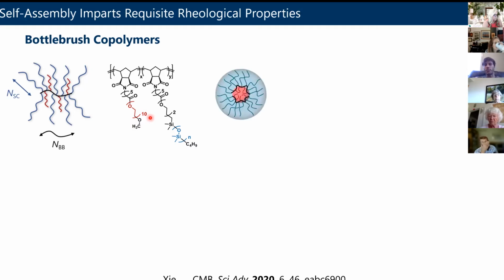Now, when you do this, if you pick the chemistry right, like polyethylene oxide and polydimethylsiloxane, they don't like each other. Those polymers, they want to be like your salad dressing. If you mix them together, they would phase separate. They would try to create layers of all polyethylene oxide and all polydimethylsiloxane. But we've linked them together with covalent bonds. So they can't create layers at the visible length scale like your salad dressing, but they try to do something similar at the nanometer length scale, where all of the red polyethylene oxide side chains will bury themselves into little micelles to get away from everything else, which is polydimethylsiloxane.